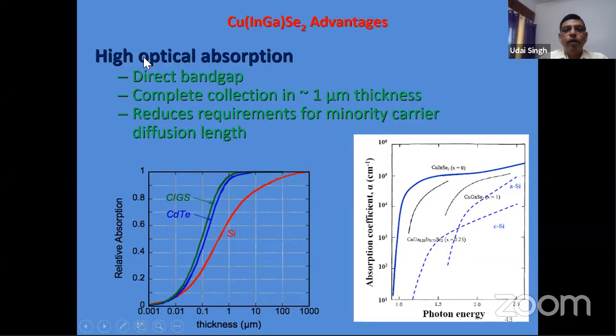Because it has a high optical absorption coefficient. If you see silicon, if you want to absorb 100% of the light, you need more than 100 microns of the material. But in the case of cadmium telluride or CIGS, you can see that with around 1 micron, you are able to absorb most of the solar spectrum. So it is a very high absorption coefficient material because they are direct band gaps. Silicon is an indirect band gap. That is one of the differences. Its optical absorption coefficient is slightly less.